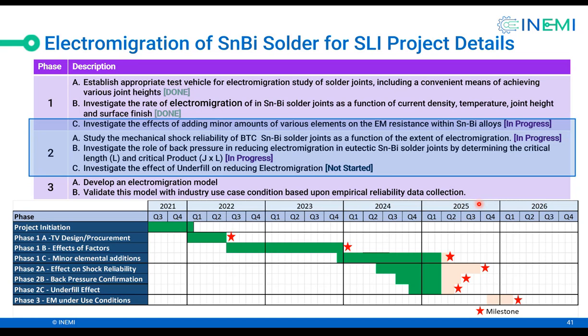Then we are going to study the mechanical shock reliability of the BTC solder joints after they have been subject to current stressing, which, as PJ showed, results in bismuth migrating to the anode end. That's one of the major concerns of the tin bismuth solder users, because that bismuth is brittle, and to begin with, the mechanical shock reliability of the joints is a little bit lower than SAC, for instance. But if you have the bismuth at one end of the joint, it could make it even worse. So that is the reason why we have 2A.